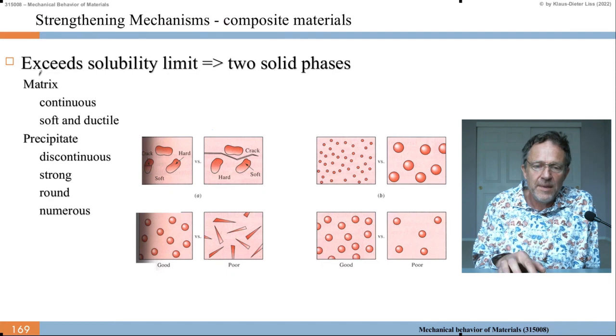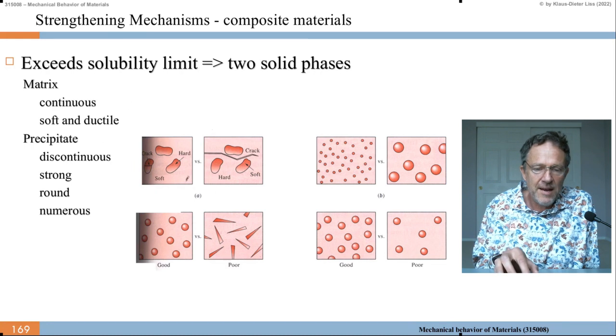So when the solute exceeds the solubility limit, then we get 2 phases. We know that already. And we can have the following situations, or the many situations here. So we can have hard precipitates in a soft matrix, or soft in hard, and then we can have the spheres, or we can have the needles. On the right hand side here we have poor mechanical properties, on the left hand side we have good mechanical properties. Poor because here at the tip of the needles we have stress concentrations. Stress concentrations may lead to cracking, yielding and cracking.